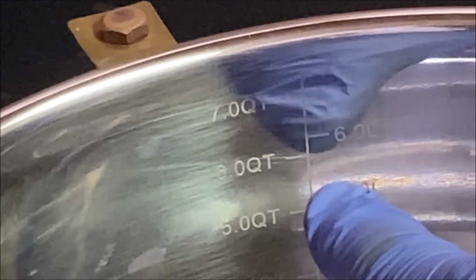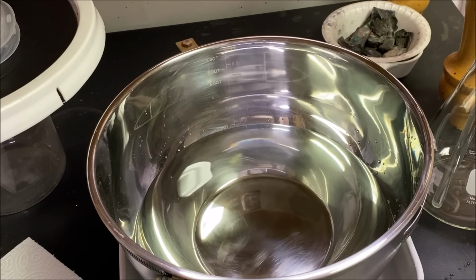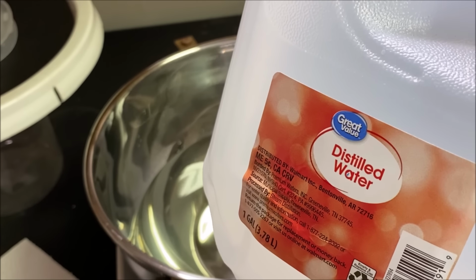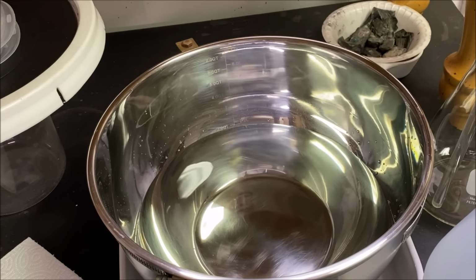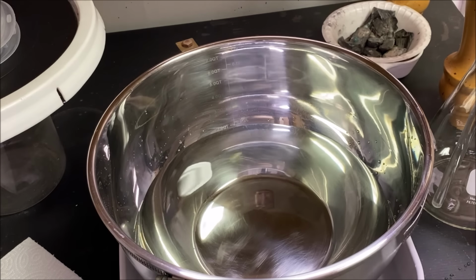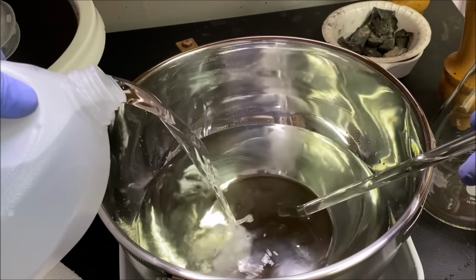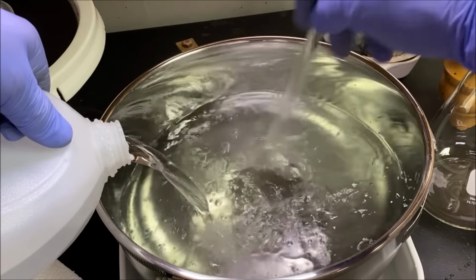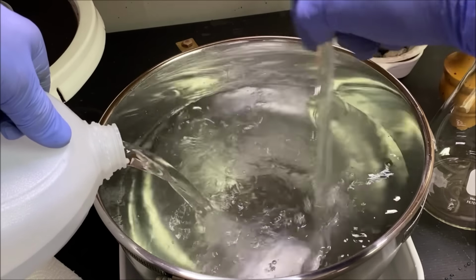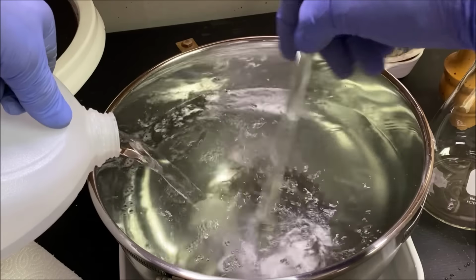Here's some markings on the back of the bowl. What I'm going to do now is add some distilled water until we get up to that 6-liter level. Distilled water. And I'll stir this up as I add the water, so we have a consistent mixture. And this should produce electrolyte that's about 150 grams of pure silver per liter concentration for our electrolyte.